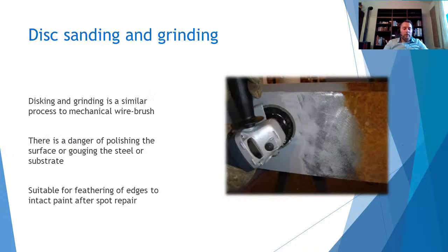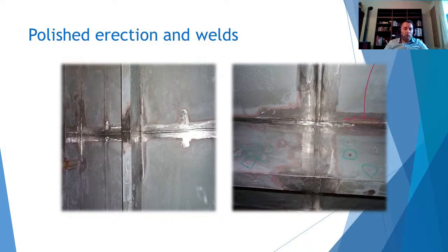Sanding and grinding are often used to prepare the surface for coating, and the machine powering this tool may be the same as those used for power wire brushing, with suitable sanding discs or grinding wheels substituted for the wire brush. Also in this case, the use of the tool, depending on the abrasive grit size, could be critical. This tool is suitable for feathering the edge of intact paint after spot repair. Here are some pictures with polished erection and welds. You can see the area around the welds completely polished. It's very important that you do this before the sandblast, because any coating remaining attached can affect adhesion on this kind of surface when you polish the surface.